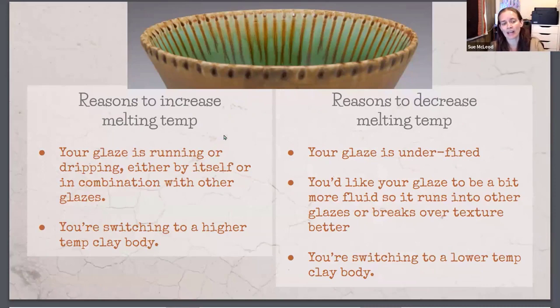So reasons why you might want to increase the melting temperature of your glaze. If your glaze is running or dripping, either by itself or in combination when you layer it with other glazes. Sometimes your glazes are fine by themselves, and then you layer them on top of each other and it becomes a runny mess. And so you could slightly increase the melting temperature of those glazes in order to reduce the amount of running, in which case I would probably just increase the silica and alumina, these high melting temperature glass formers, which proportionately lowers the fluxes, and that's a way you can increase melting temperature.